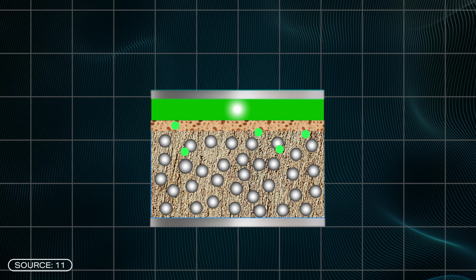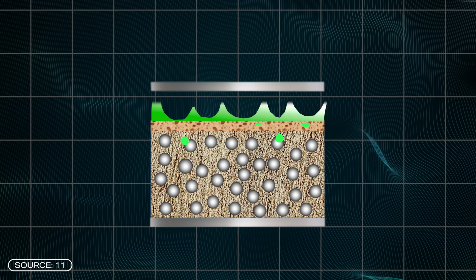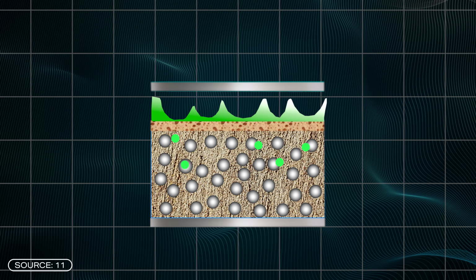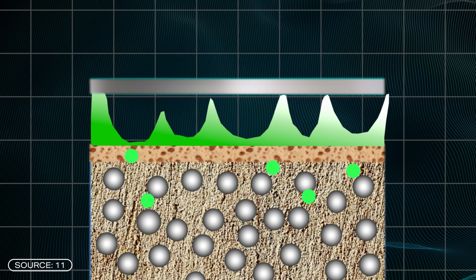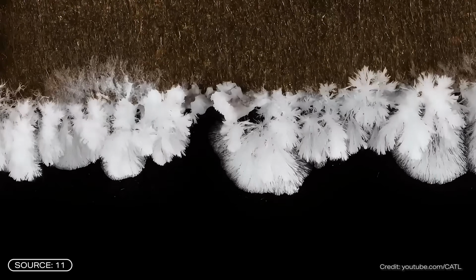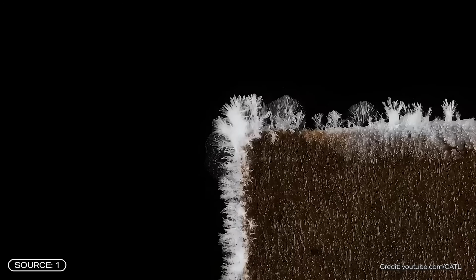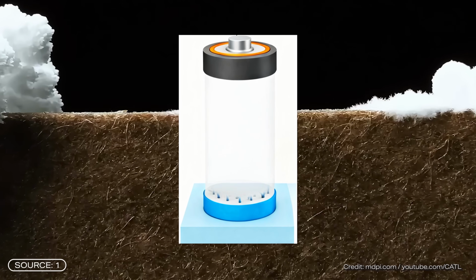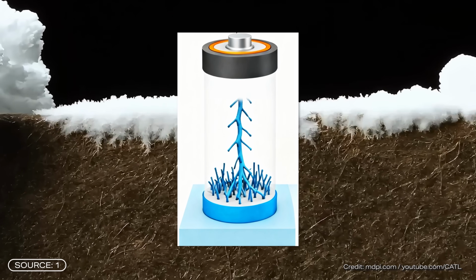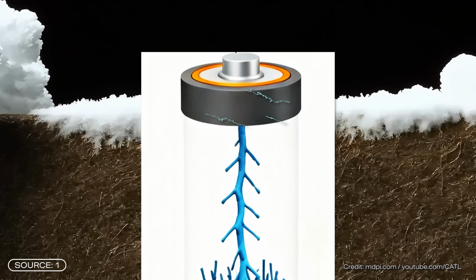The uneven distribution of lithium on the surface creates something like small lithium mounds. This leads to current hotspots where the lithium is particularly likely to continue growing in the next cycle. And this then can contribute to a well-known problem in battery technology, dendrite formation. You can imagine dendrites as small lithium branches. These branches can pierce through the electrolyte and by that cause short circuits, among other things. Admittedly, this heterogeneous surface is not the only factor that triggers dendrite formation. Other factors include, for example, an unsuitable electrolyte or poor lithophilicity, that is a tendency of the current collector and the lithium to react evenly with each other.